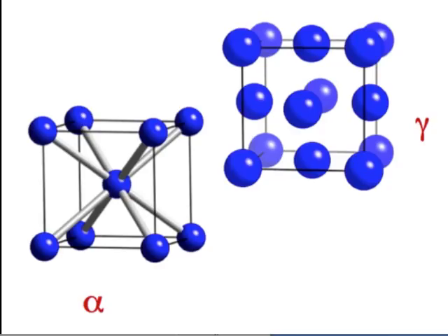Okay. So these are the structures that we are going to consider. First of all, we have the austenite, which is cubic F, and then the martensite, which we'll assume to be either body-centered cubic or body-centered tetragonal if we have some carbon in the material. So it's perfectly possible to get martensitic transformation in pure iron. It's got nothing to do with the presence of carbon. It's the mechanism by which you transform the parent into the product. You'd have to cool at an incredibly high rate because the hardenability of pure iron is negligible. So we do experiments where we cool at 1,000,000 degrees C/s, and we can see the martensite forming in pure iron.